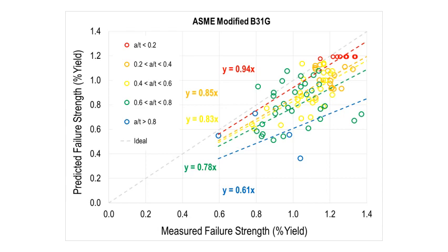So what that means is, as I go from a shallower flaw, where I'm relatively speaking fairly accurate in my modified B31G prediction, to the deeper flaws, I'm actually getting increasingly conservative. Now, increasingly conservative might mean that I'm safer, but it might also mean that I'm digging up a lot of stuff that I really don't need to dig up as a pipeline operator.